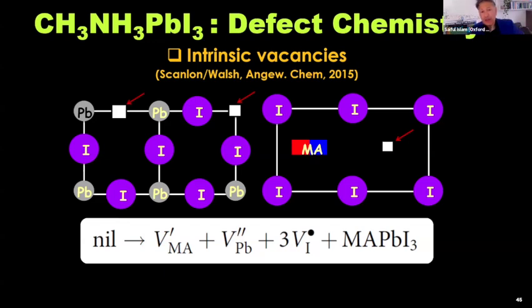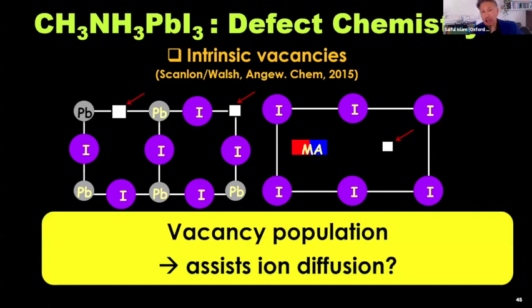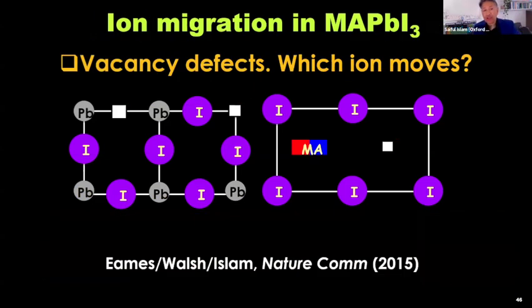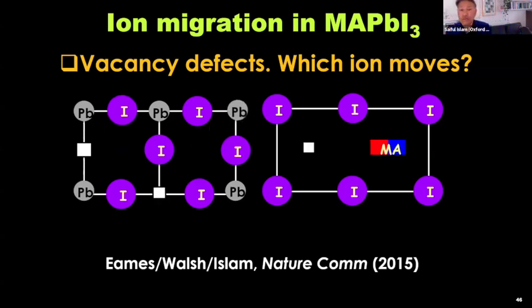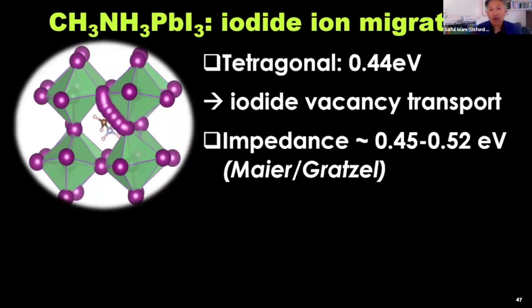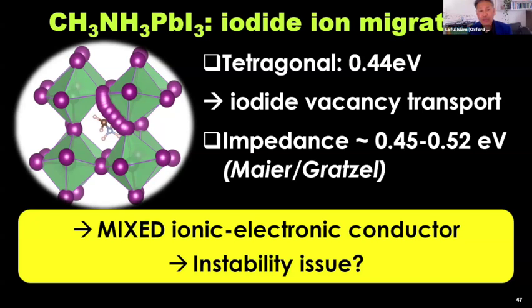So this is a slice through the structure. If there are vacancies, could they assist ion diffusion, which we don't want? These are semiconductors. We want just electronic transport. So we looked at ion migration in this material. But which ion moves? Is it the iodide that moves? Is it the lead that moves? Or is it the methylammonium that moves? Through our atomistic modeling, we found out very early on that it's the iodide ion that migrates, with a migration barrier of about 0.4 electron volts, 40 kilojoules per mole, which is fairly low. That prediction, which we had before experiment, was confirmed by impedance spectroscopy by Joachim Maier and Michael Grätzel, and they found a very similar value. So the conclusion here is that these halide perovskites show mixed ionic electronic conduction, and that could be an instability issue.